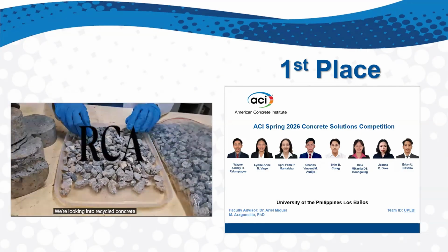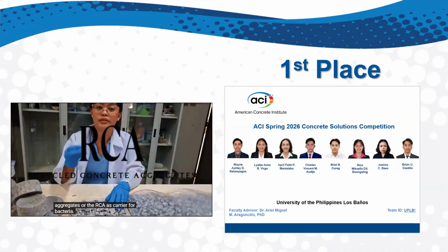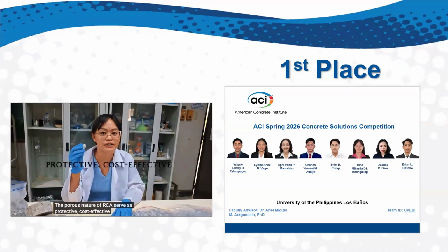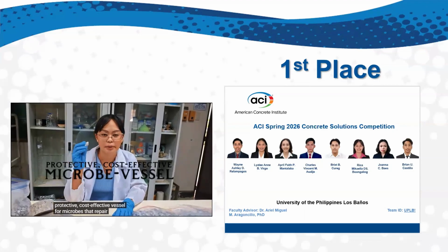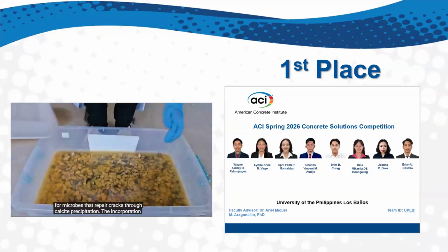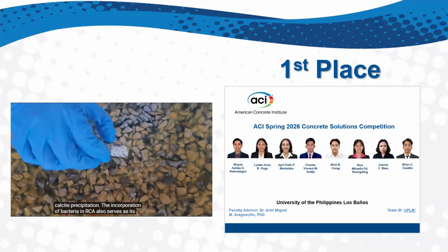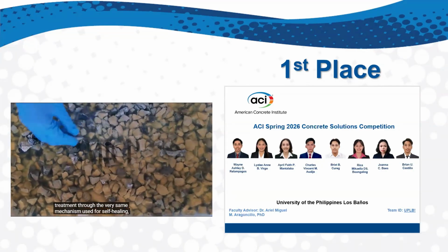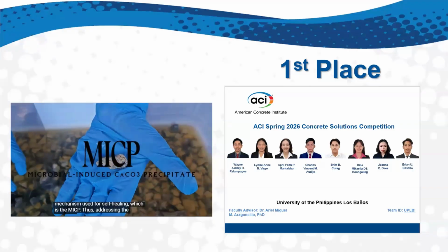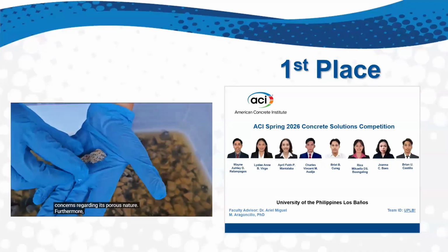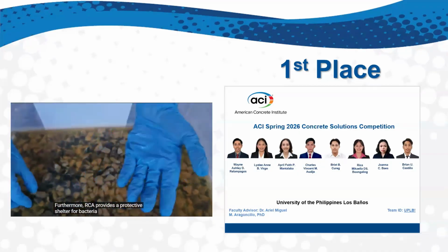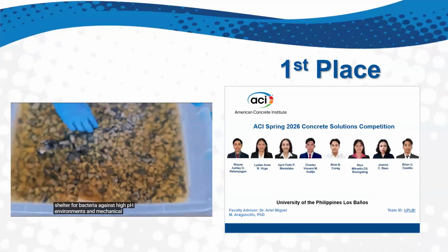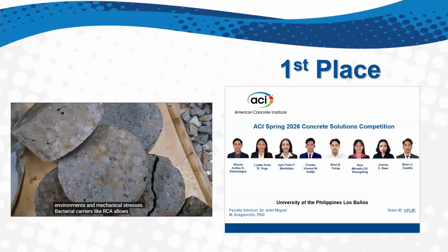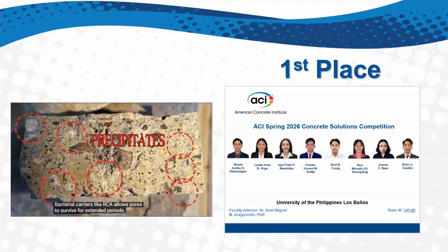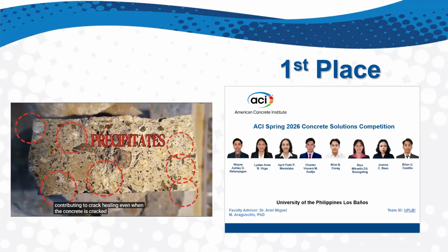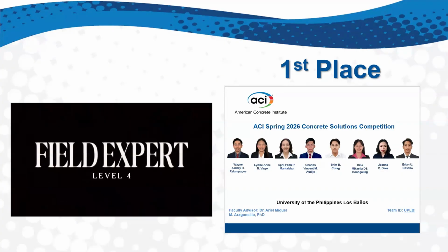We're looking into recycled concrete aggregates, or the RCA, as carrier for bacteria. The porous nature of RCA serves as protective, cost-effective vessel for microbes that repair cracks through calcite precipitation. The incorporation of bacteria in RCA also serves as its treatment through the very same mechanism used for self-healing, which is the MICP, thus addressing the concerns regarding its porous nature. Furthermore, RCA provides a protective shelter for bacteria against high pH environments and mechanical stresses. Bacterial carriers like RCA allow spores to survive for extended periods, contributing to crack healing even when the concrete is cracked at later stages.